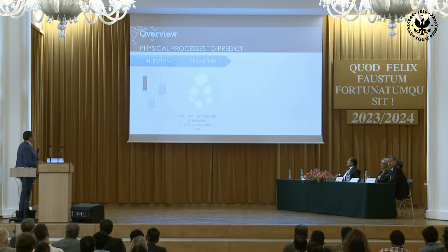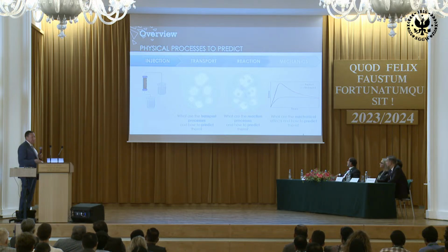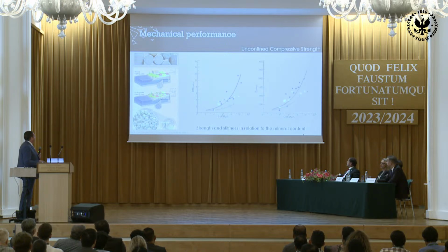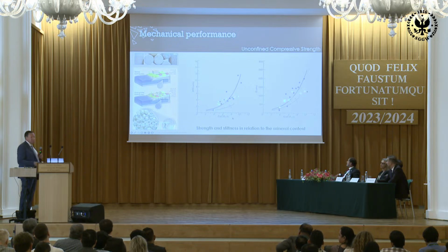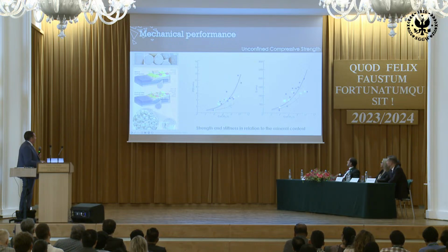So I discussed the injection process, I discussed the transport, I discussed the reaction. So the last remaining item is the mechanical behavior. How much strength are we getting after our injection? Here are unconfined compressive strength tests that we did a long time ago. And basically what you see is that we have an increase of the compressive strength with the increase of the amount of calcite precipitation that you put in the ground. The same thing with the stiffness. This is Young's modulus versus the calcite precipitation.